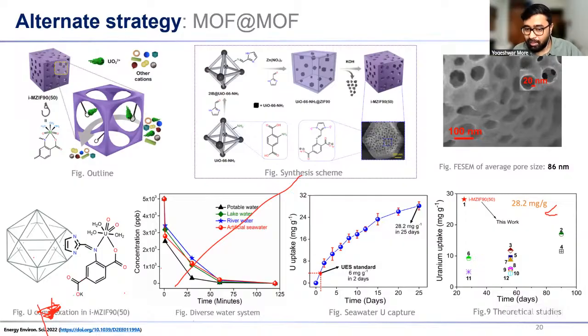But we are facing problems commercializing this, which I will discuss. So in these 2 days, the US standard was only 6 milligram, which we achieved in 2 days, and using 25 days we are able to get 28.2 milligram of uranium per gram of sorbent. So it is a very high amount of uranium recovery from seawater. And when we compare in the commercial domain, this MOF has the highest uranium uptake right now, among commercially available materials or MOF materials.